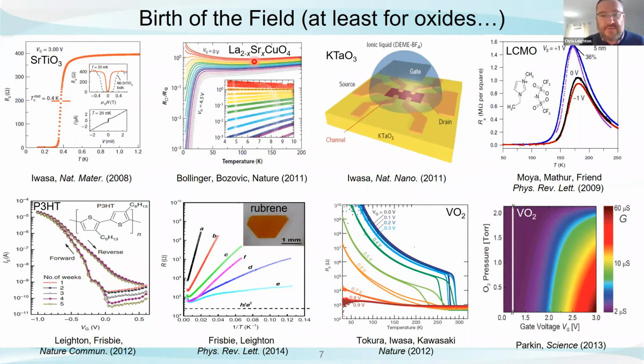Subsequent to that, there were some beautiful experiments done controlling superconductivity in the cuprates. This technique was used to discover superconductivity in potassium tantalate. And of course, it wasn't long here, this is over 10 years ago, that the first experiments were done on manganites. This is lanthanum calcium manganite, where it was shown that you can manipulate the Curie temperature by 10 or 20 Kelvin by applying a gate voltage, okay? A couple of colleagues and I got heavily into this in organic semiconductors. I won't dwell on that, but I will dwell on this interesting situation in vanadium oxide, right?